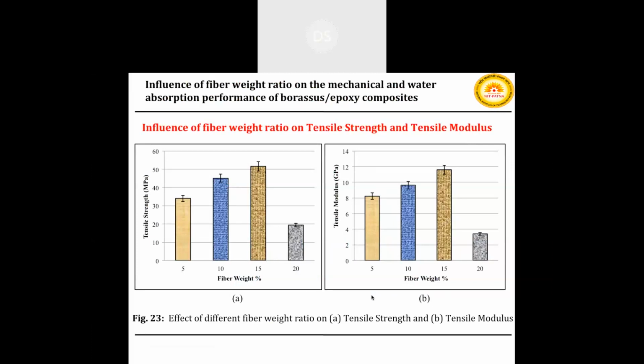Next, influence of fiber weight ratio on the tensile strength and modulus. The tensile strength of developed Borassus fiber epoxy composite with different weight percentages, 5%, 10%, 15%, and 20% of fiber, was used. In figure A and B, as the Borassus fiber weight ratio increases, the tensile strength and modulus increase up to 15% weight ratio. Further increase in weight ratio of Borassus fiber above 15% decreases the same because of the shortage of resin material due to the lower interfacial adhesion between fiber and matrix.